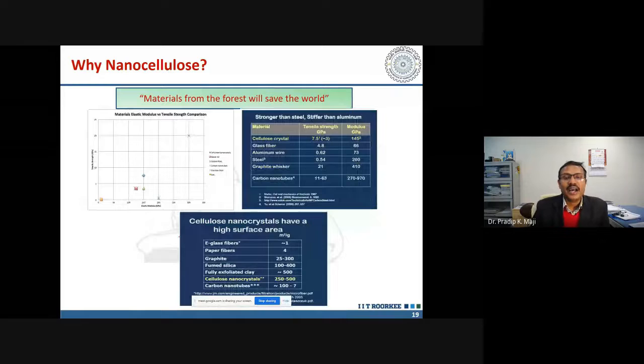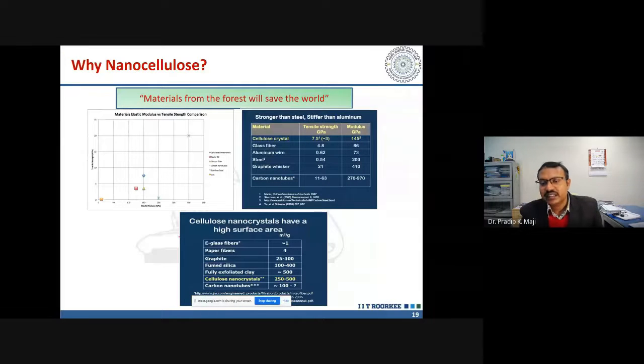I'm comparing nanocellulose with competitive materials, like nanocellulose or nanocrystal. In terms of mechanical property, tensile strength is 7.5 GPa, and modulus is 145 GPa. Compared to glass fiber, aluminum wire, steel, graphite whisker, and carbon nanotube, our material is much better than glass fiber, aluminum fiber, or steel. Steel's specific strength is very low, but cellulose nanocrystal's specific strength is very high. However, carbon nanotube material's mechanical property is much higher than cellulose nanocrystal.